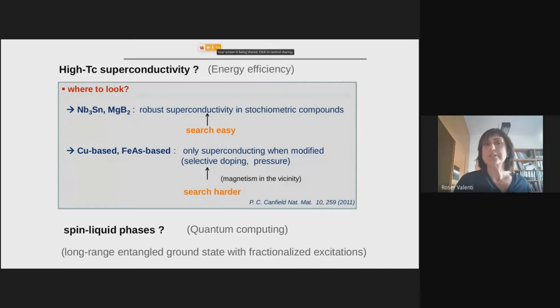However, for the materials I showed to you, we manipulate the systems in order to obtain this high TC superconductivity, in the copper base, in the iron arsenic base, or in this twisted bilayer. We had to either dope the system, put the system under pressure, or start twisting. So this is a much harder search if you want to start from this periodic table.